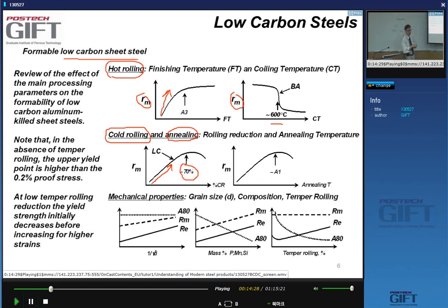That's one thing. Second thing is the anneal. When you do the annealing, it's important to increase the temperature at which you carry out the annealing, but you cannot heat up so high that you start transforming the steel back to austenite. If you do this, so you heat up above A1, the texture improvements disappear and your R value decreases again.